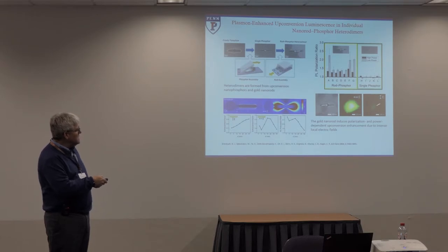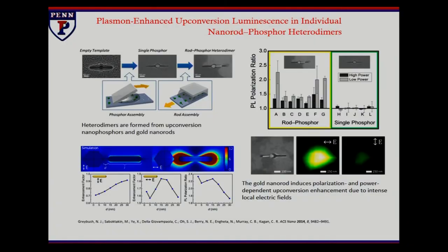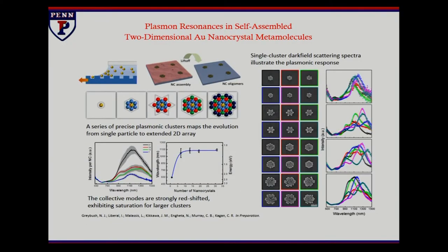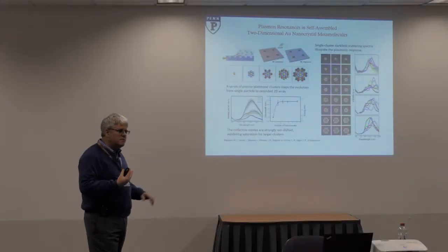But if you send light in that is polarized perpendicular to the antenna, it doesn't couple to the light field, and so you don't get any enhancement, because you haven't developed a strong electric field to drive that plasmon resonance. And so these kinds of structures with the templated assembly allow us to bridge between systems.